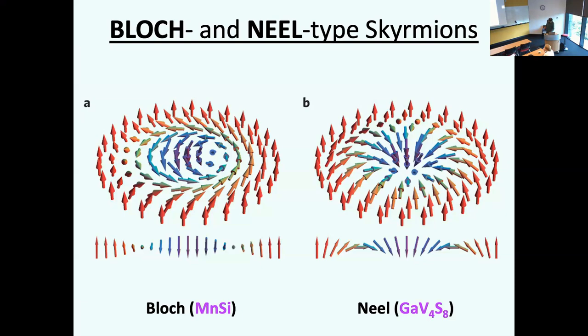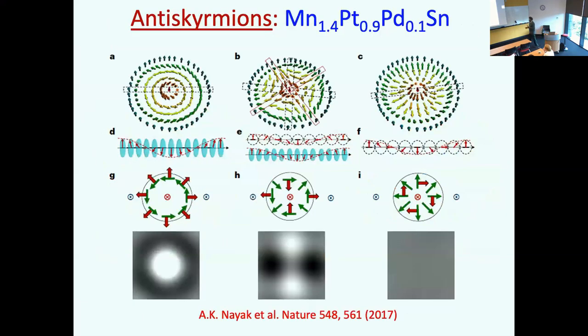So that was seen already in 2009, but people were looking for, can I get anti-skyrmions? It took 8 years; manganese, platinum, palladium, tin, they had to figure out, and they were able to experimentally observe the anti-skyrmion. So what's an anti? Like vortex, anti-vortex, but what is it here? So I said, if you cut it here, this is a Bloch skyrmion, this is a Néel skyrmion. If you cut it here, you get this helical domain wall. If you cut it here, you get cycloidal. If you do Lorentz transmission electron microscopy, LTEM, on this material, for chirality here, you will see this blob. Because there's no chirality here, there's no combing here, you see nothing. This is a combination in between somewhere.